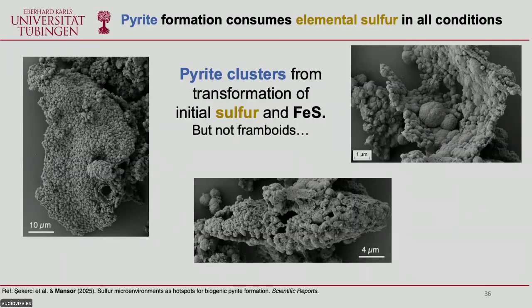So these pyrite clusters, here are some images where you can see better. This is a really large pyrite cluster. This is a typical shape of an elemental sulfur particle, but it has been fully replaced with smaller pyrite. And this is the shell that I've shown you before.